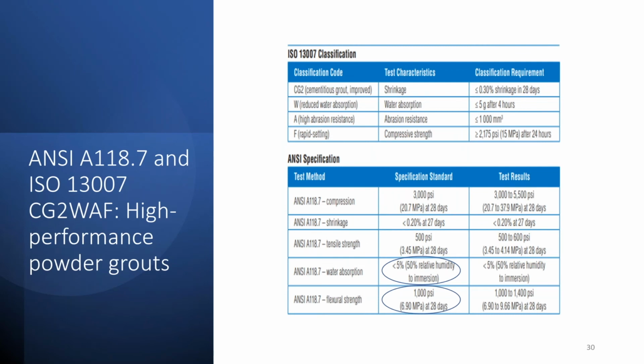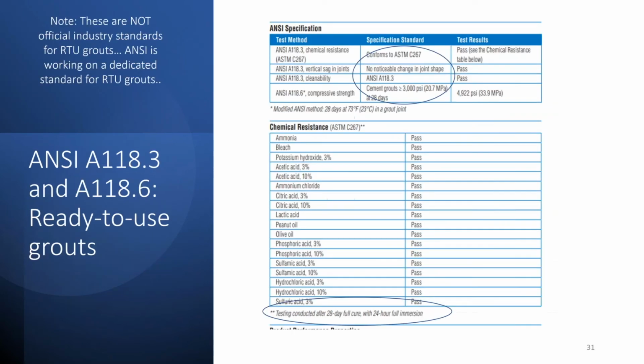And looking at 118.7, which we just did, going on to RTU grouts, the key thing here is probably its extensive list of chemical resistance results, all passing. And these are not easy acids, et cetera: sulfamic acid, hydrochloric acid, sulfuric acid, that it's passing after 28 days of exposure or immersion. And that's making a test sample and just dropping it into these various chemicals. So it's very impressive, and it's similar, not identical, to what we see with epoxies.